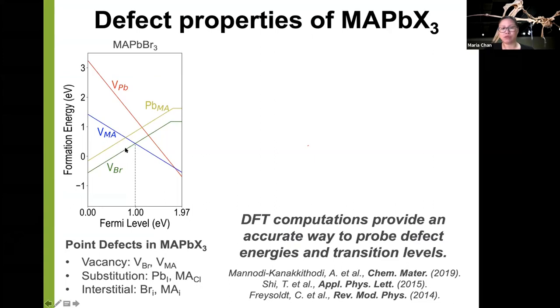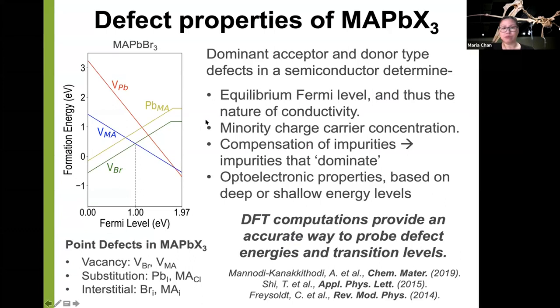The methylammonium vacancy is negatively charged — that's why it goes down. There is a dashed line which is the point where in the absence of other dopants, the positively and negatively charged defects are at the same energy — the same number. So this dashed line gives the Fermi level of the intrinsic material. We use these plots to find which defects are dominant, and what controls the type of charge carriers in the material. We can also put in the formation energy of extrinsic defects to find out what the energies are, and if some are below the bromide vacancy, they may be able to shift the Fermi level.